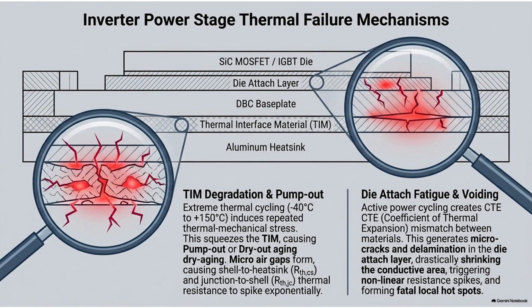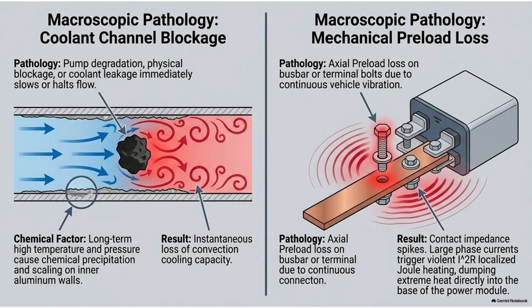This is a phenomenon known as power cycling. So it's constantly heating up and cooling down. Exactly. The chip heats up violently when you step on the gas and cools rapidly when you let off. Now, this silicon carbide chip has to be physically and electrically attached to that copper substrate we talked about earlier. And they do that with a die-attach layer, which is essentially a specialized glue, right? Usually some kind of high-performance solder.